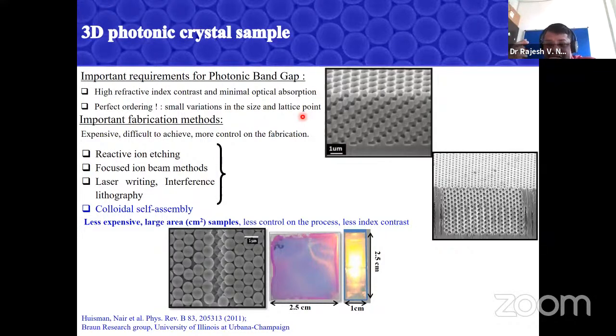So one of the things we need is a high refractive index. And nature does not allow arbitrary refractive index. The maximum you can have is 3.5 at 1.5 micron wavelength. And the material should not absorb light. That is another difficulty in finding materials. And the most important, the fabrication challenge, is perfect ordering. Even a small variation, a small discrepancy in the ordering, will kill all the optical features of the system. It looks nice in some pictures, but it never gives you any optical response when you do experiments in the lab.